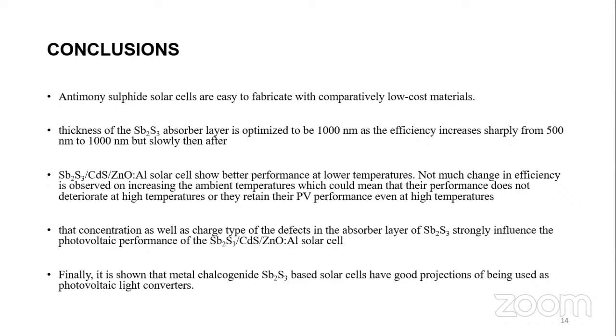This structure of solar cells, the Sb2S3 series ZnO-Al structure, shows better performance at lower temperatures also. But as we have seen, there are not many changes observed on increasing the ambient temperature, which means that their performance does not deteriorate at higher temperatures, or we can say that they retain their PV performance even at higher temperatures. We can also conclude that the concentration and charge type of defects should be highly controlled when synthesizing these types of solar cells, because they strongly influence their performance.